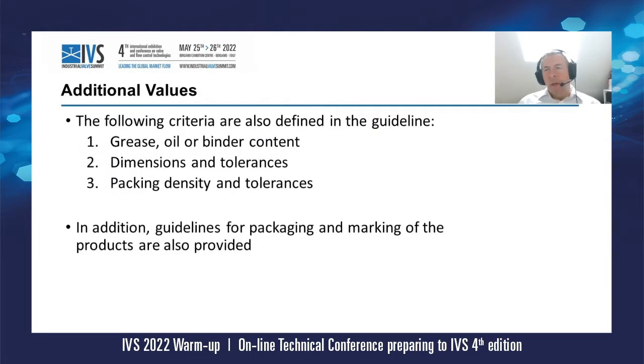Besides the specific values shown in the previous slides, other criteria are also defined in the guideline. For example, for the pump packings, the grease, oil or binder content shouldn't be too high, because a high amount of grease, oil and binder will give quite high creep relaxation or volume loss, and the packing won't last that long in the application.